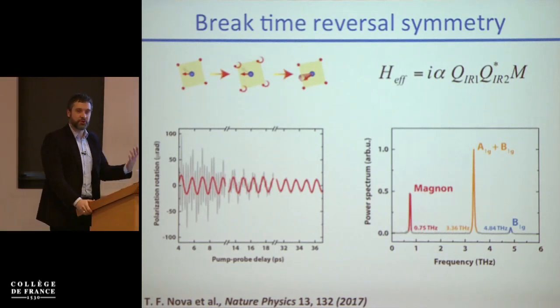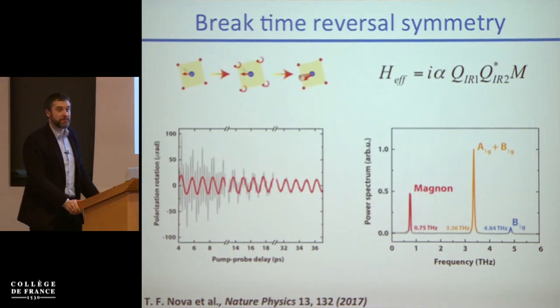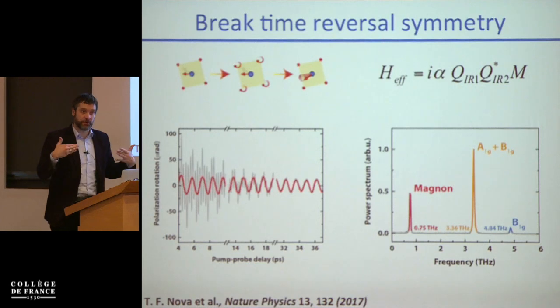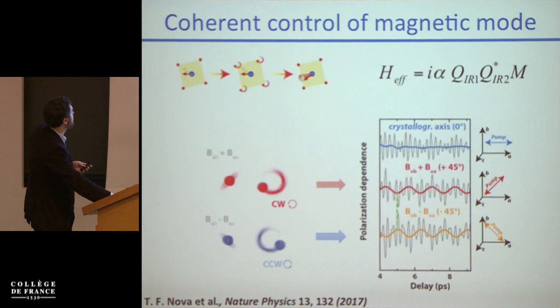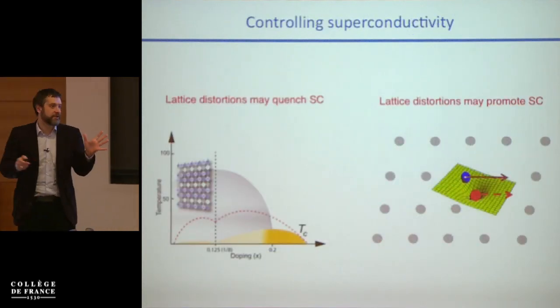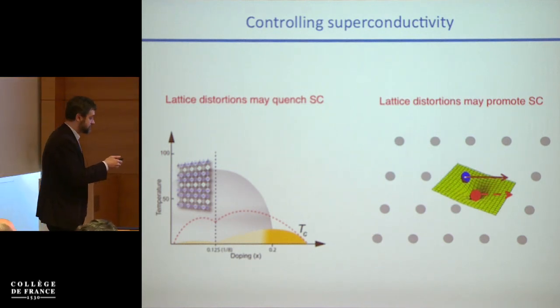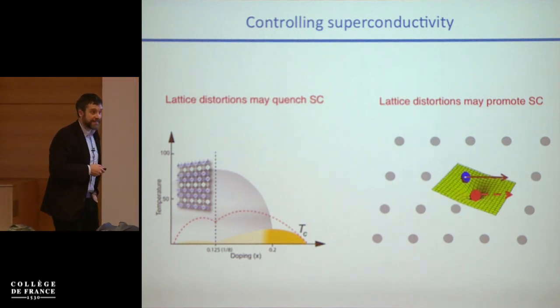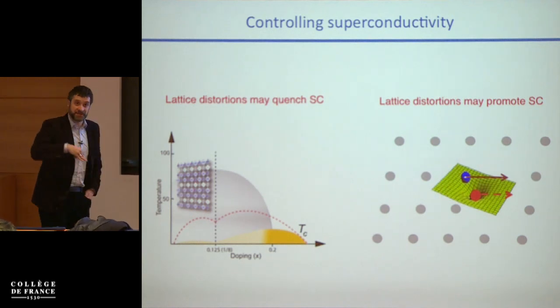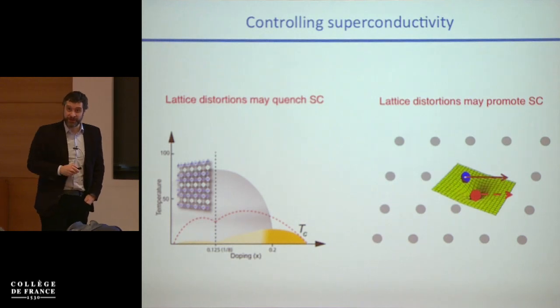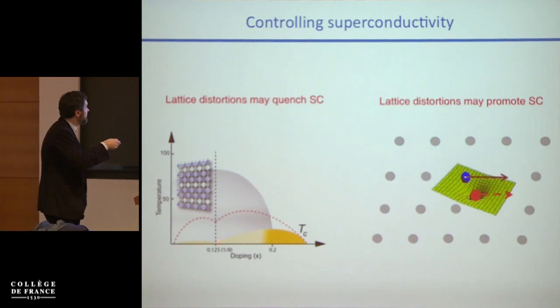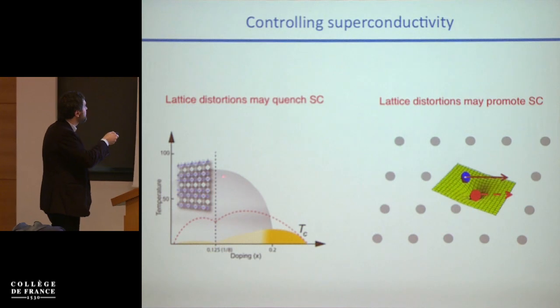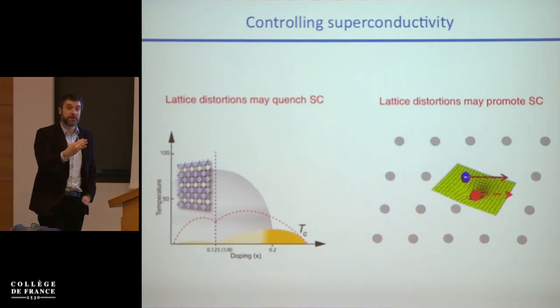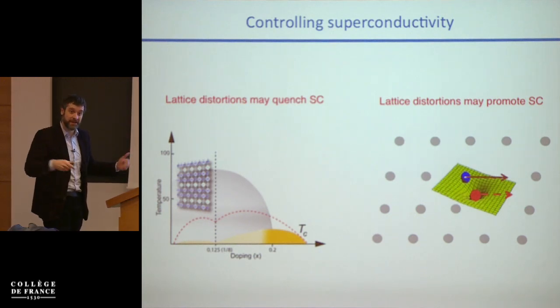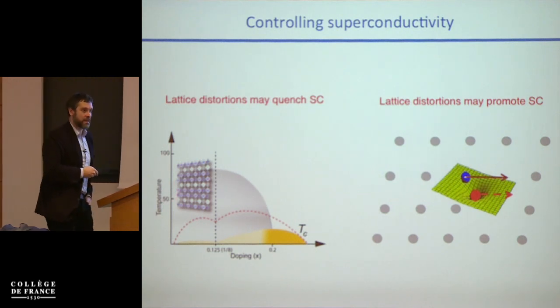Okay, and I'll elaborate more later. So the next part is going to be phononics in superconductors, basically. And the reason why one might be interested in phononics in superconductors is, even very generally, one could say that in some materials, such as the high TC cuprates, one knows that some lattice distortions are sometimes instrumental in quenching the superconducting transition temperature. This is, for example, known at specific dopings in some cuprates, in which one has, for example, stripe orders that become the ground state of the system and quench the equilibrium superconducting state. And so in that case, one may think that by exciting the phonons in the correct way, one might be able to melt these competing orders, as I will elaborate on later, and increase TC.